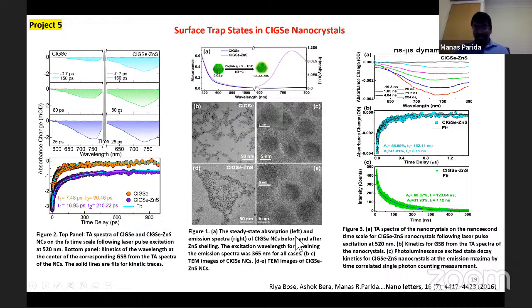Particularly these two pictures, if you compare them, there is one type of shelling happening, meaning you have a core nanoparticle. Here, this is CIGS, like copper indium gallium selenide. The core nanoparticle, and then you are shelling, meaning you are covering with zinc sulfide. In that way, here also we somehow enhance the efficiency of the solar cell.